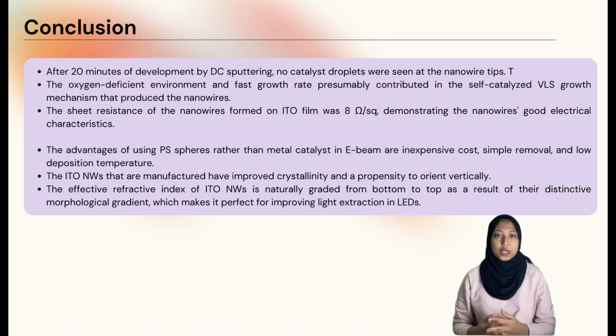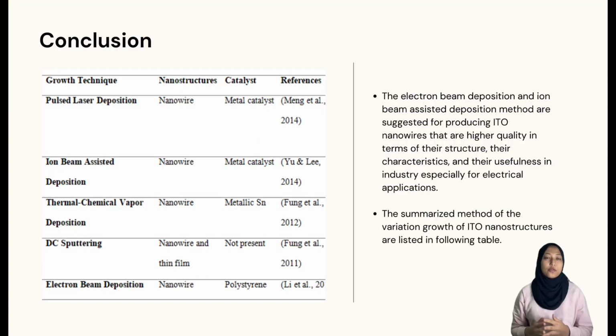Moreover, the sheet resistance of the nanowires formed on ITO film by DC sputtering was 8 ohms per square, demonstrating the nanowires' good electrical characteristics. In addition, the advantages of using PS spheres rather than metal catalysts in E-beam are inexpensive cost, simple removal, and low deposition temperature needed. The ITO nanowires that are manufactured have improved crystallinity and a propensity to orient vertically, which makes them perfect for improving light extraction in LEDs. Based on the results of this study, the electron beam deposition and ion beam assisted deposition methods are suggested for producing ITO nanowires that are higher quality in terms of their structure, their characteristics, and their usefulness in industry, especially for electrical applications.